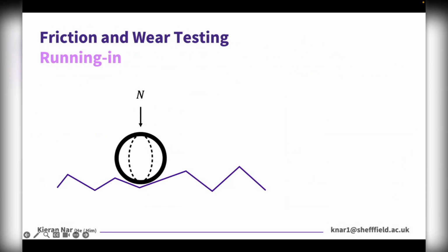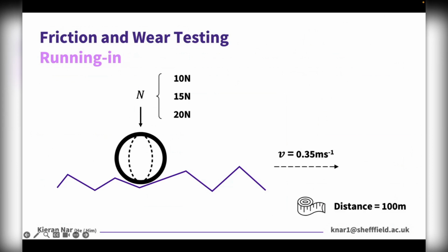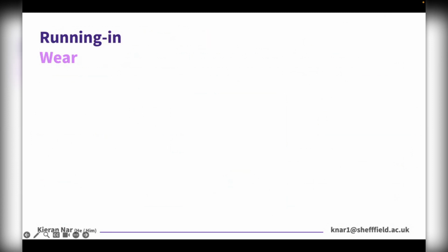So the first sliding related study that I performed focused primarily on the running in behaviors of laser sintered nylon 12 top and bottom surfaces. So this was to establish what happens when these surfaces are first subject to dynamic contact. And as you can see, multiple tests were performed at 3 different normal loads, so 10, 15, and 20 newtons.